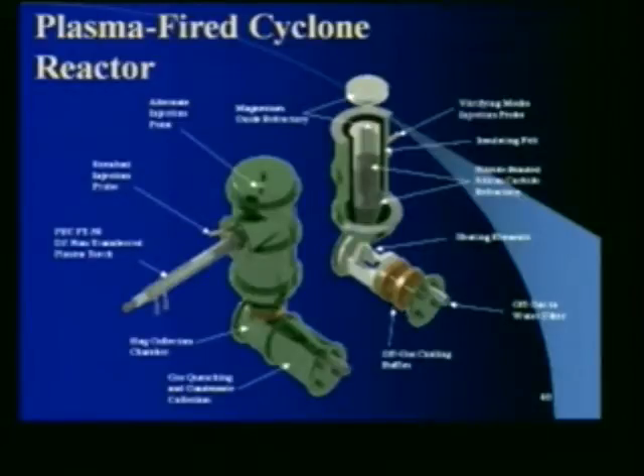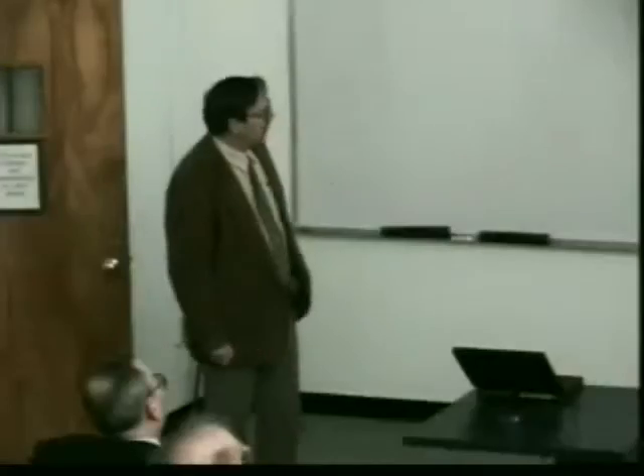There's a plasma torch. In this case, it's a 50 kilowatt Plasma Energy Corporation non-transferred arc torch attached tangentially to a cyclone reactor. If you look at the internals, let's start here. The simulated radioactive waste is injected near the plasma flame, where you get nearly instantaneous dehydration and calcination reaction. A little bit lower down, you inject the glass-making frit. It forms a liquid falling film of glass. Because of the cyclonic flow, the dust is thrown to the wall, where it's captured by this falling film of glass and goes down to a chamber below, where it's collected in a temperature-controlled environment. The off-gas then goes off into the gas treatment system.